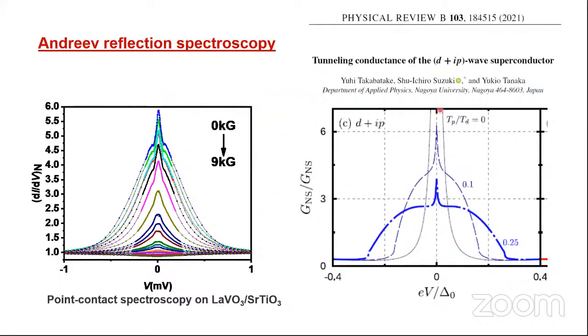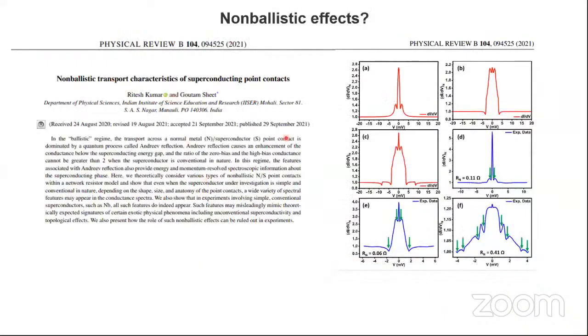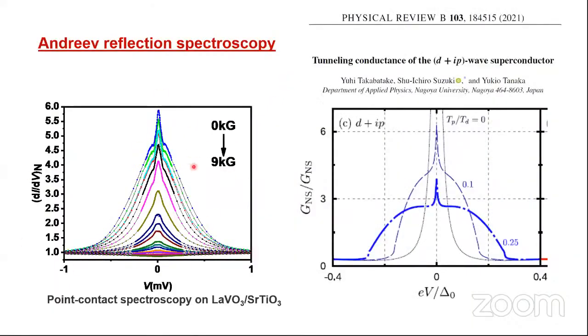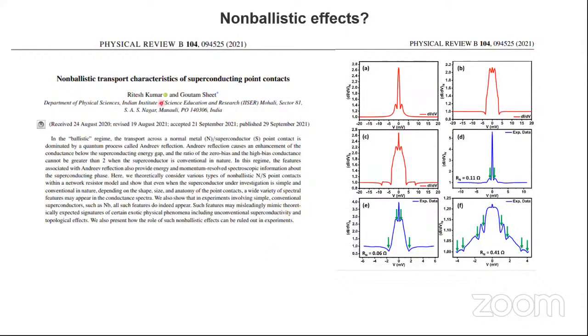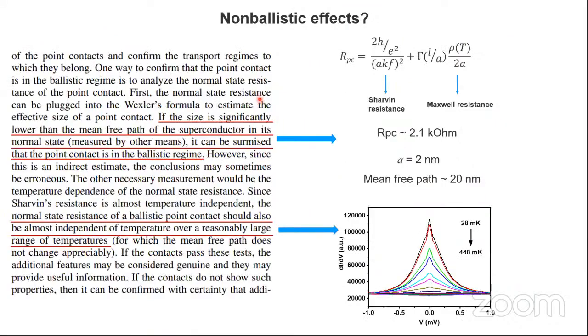Now, we compared this with some of the calculations done using unconventional order parameters, where it is possible that the low bias conductance is much larger than the high bias conductance, much greater than 2. But we also need to be careful because we know that such things often appear if the point contacts are not made in the ballistic regime of transport. In our case, we found this consistently for all the 6 contacts that we measured on LVO STO. And we recently talked about these aspects of non-ballistic effects in point contact spectroscopy in a PRB paper in 2021, where we also mentioned how we can rule out the contribution of non-ballistic effects.